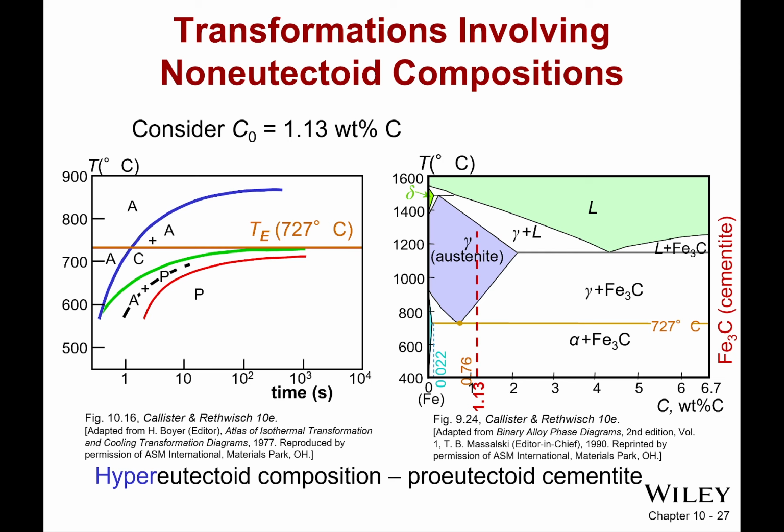So it told you that it had 0.45%. So I'm right here. This is that line I'll be having for 0.45% on this diagram, which means I have too much ferrite. I'm not where I'm supposed to be. I should be right here. I am actually over here. So I'm going to have more ferrite than I'm supposed to have. This is a hypo-eutectoid composition, and so I would have pro-eutectoid ferrite. So no, that's not an error with the slide. I'm just pulling a slide from earlier, which was a different example.